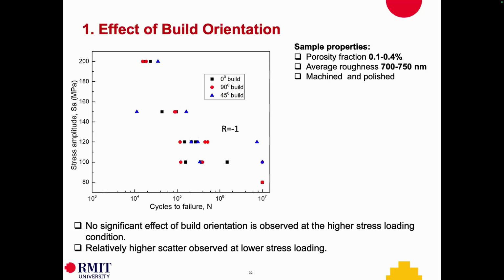Okay. So the first challenge I mentioned, build orientation, and what we saw there. Look at this plot. This is stress amplitude versus cycles to failure, fatigue life. This is R = -1, completely reversed loading. With stress amplitude, of course, if the stress amplitude increases, the fatigue life decreases, as we see at high amplitude.